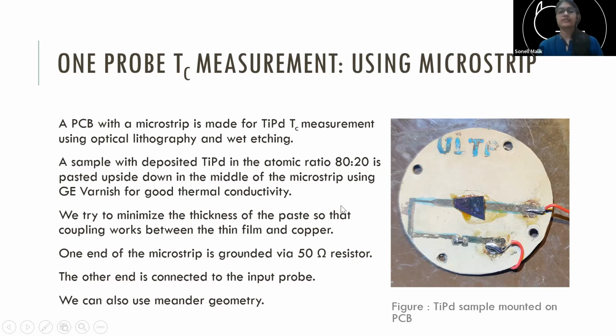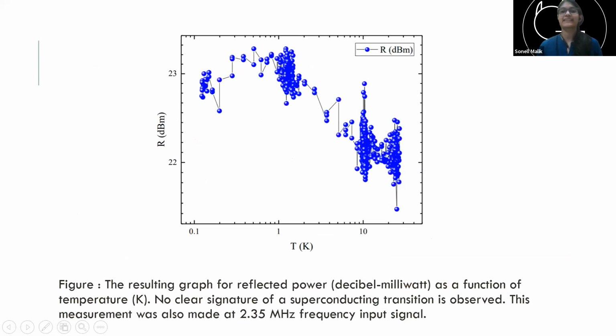So here I checked for TIPD, and the results were not very exciting. We got a very random graph for reflectivity and essentially no clear signature that there was a transition to superconductivity. This also we did at the same input frequency signal. This could also be because magnetic coupling is a much weaker phenomenon to rely on.